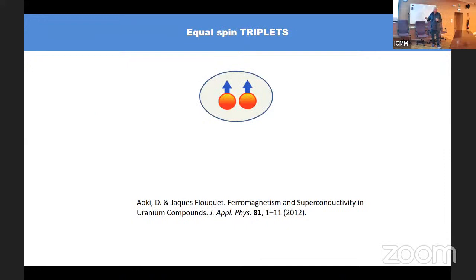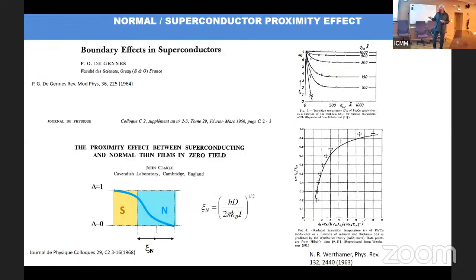But on the contrary, triplets, which may exist, if they are equal spin, may coexist with ferromagnetism peacefully, right? But triplet superconductivity has been found very rarely in bulk samples either, with well-known exceptions in uranium compounds examined by Jacques Flouquet. But in the framework of the proximity effect, these triplets can be generated quite naturally.